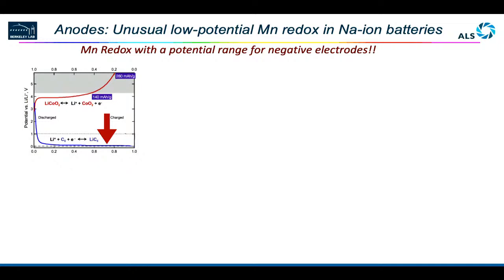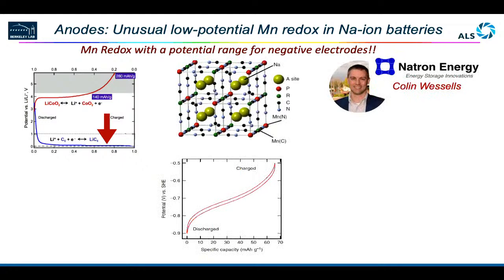So of course, in most cases we can resolve the transition metal state by just X-ray absorption. Sometimes you need to do more careful experiments. But in some other cases, if the transition metals go beyond the conventional range, then we probably will have a problem with just X-ray absorption.